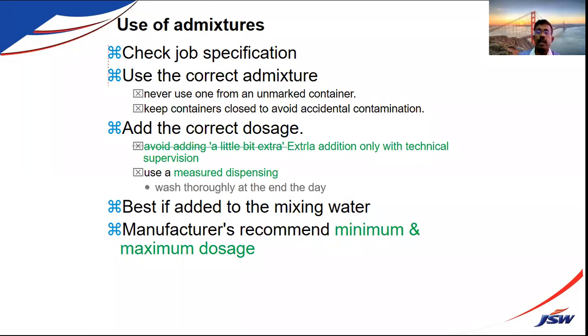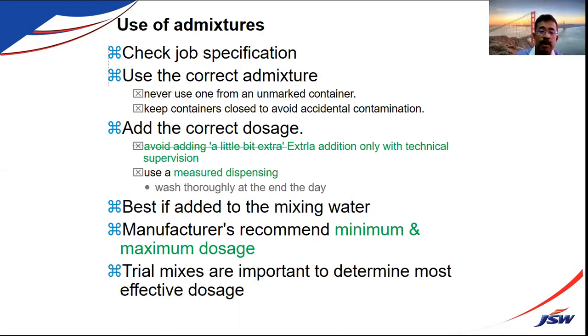And manufacturers recommend minimum and maximum dosage. When you're using admixtures, they give what should be the minimum dosage, what should be the maximum dosage. So as per those guidelines, you have to use the admixtures. And it need not be the same for all the admixtures. Different companies have given different formulas. Their manufacturing process is different, formula is different, blending of chemicals is different. So based on the manufacturer's recommendation, we should go. With many RMC plants, I find they go with a common dosage of admixtures, 0.6%, 0.7%. That should not happen.